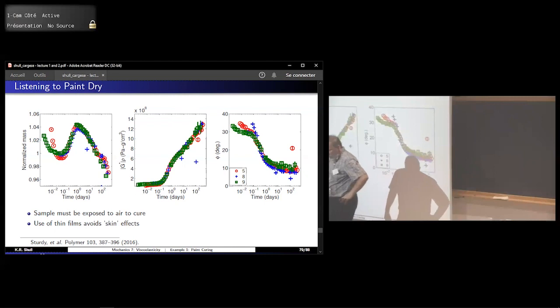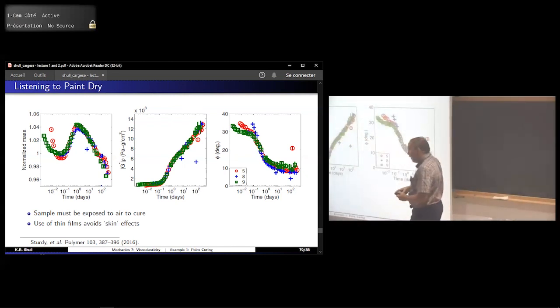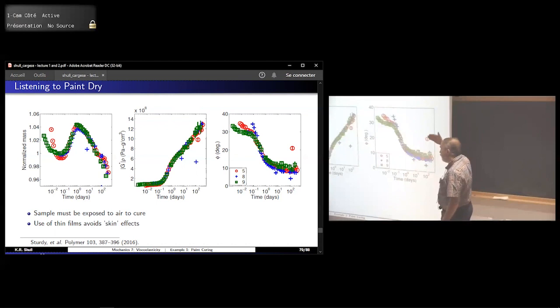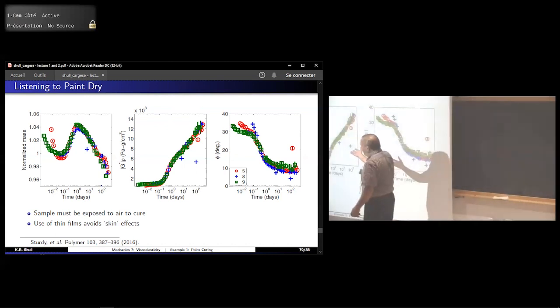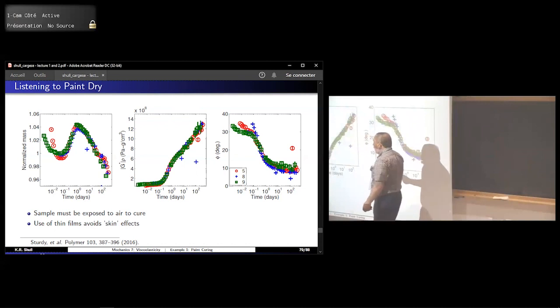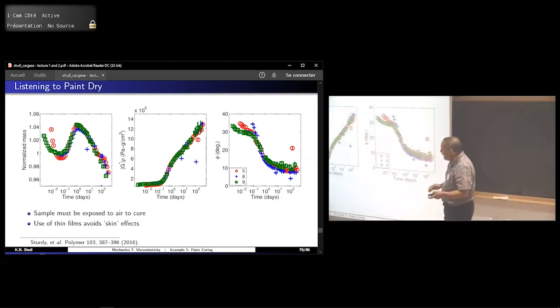Yeah, I mean, we spent a lot of time on this. It's basically behaving as an acoustic reflectometer. The equations to do this are very similar to equations to model a reflectivity experiment. So you can have stacked up layers and assume you have different properties. It turns out what you're measuring is really an average all the way through. But you can look at how much that average is affected by non-uniformities, and there's not enough information in the experiment to unambiguously say what they are. So we can't say definitively that this thing is uniform all the way through.